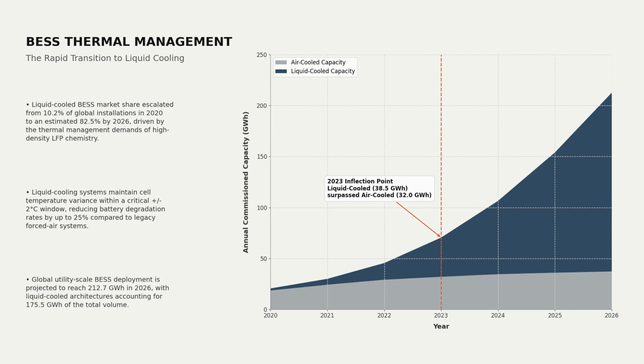This shift is driven by the need to maintain cell temperature variance within a strict plus or minus 2 degrees Celsius window. Exceeding this thermal threshold accelerates capacity fade and risks catastrophic thermal runaway. Maintaining this precise temperature window reduces battery degradation rates by up to 25%. By 2026, liquid-cooled systems will account for 175.5 gigawatt-hours of the projected 212.7 gigawatt-hour global market.